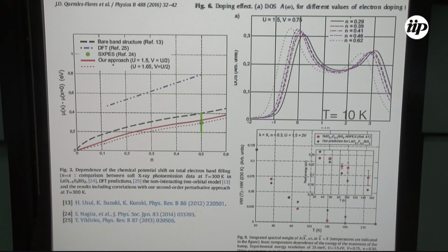Our second order approach for the spectral properties also allows us to compare the results we get for the chemical potential shift as a function of filling. And actually, this point is the result which was obtained in photoemission. And we are comparing with, this is DFT. So DFT alone is quite far away from the experimental point. The two orbitals by Usui, let's say the bare band structure, give you this kind of chemical shift as a function of doping. And when we use the second order approach, including the correlations, you start getting really very close to the chemical shift. So actually, it's capturing that, which is actually something quantitative.